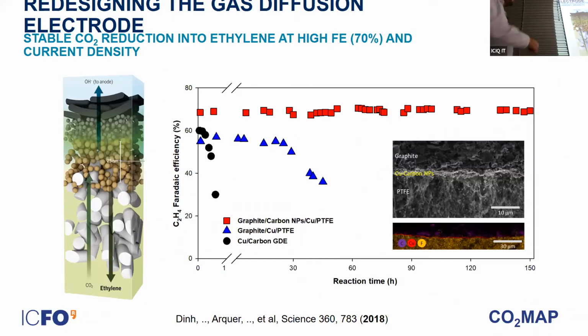So we thought of redesigning the catalytic electrode in such a way that you change the roles of everything. So instead of having a conductive carbon paper in the bottom, which is responsible for charge transport and is responsible for hydrophobicity, we just put the best material for hydrophobicity. We just put a PTFE gas diffusion layer. We deposited the catalyst on the top, and then we just design the current collector on top. So this is a combination of carbon nanoparticles and graphite. And only when we inverted this kind of structure, we could achieve efficient and stable operation.